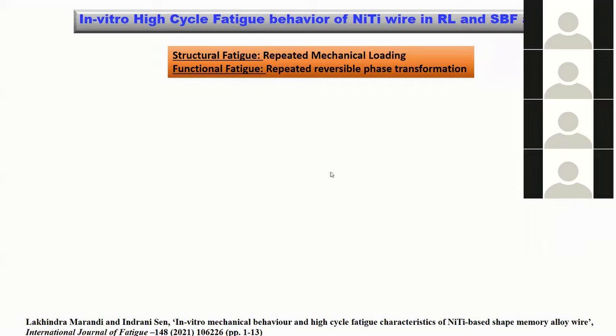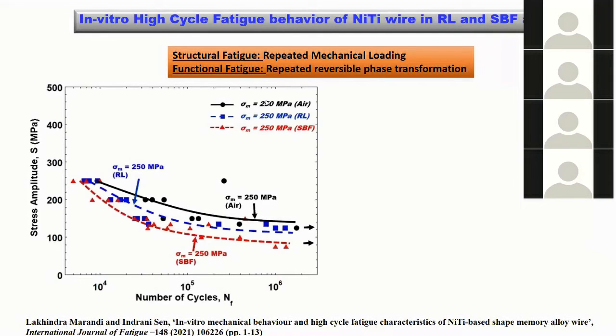So if we are loading and unloading, the austenite is converting to martensite and back to austenite and back to martensite and so on, right? That also leads to another kind of damage in these materials, which is called functional fatigue. These two are very significant for shape memory alloys in general, and we tried to figure out the effect of this. This is just the overall results of the study that we got, and this is a typical SN